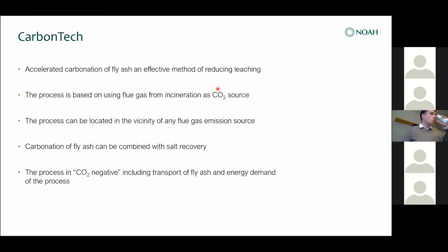And what is also important to us is that we can combine the carbonation of fly ash with salt recovery, because we can stabilize the fly ash first and then recover the salt later on. Always when we look at processes, we do life cycle analysis, and we also did that for the salt project, and it looks very good. This process is also overall CO2 negative. It means that we can capture more CO2 than we emit, including transport and the energy amount of the process. So it's a permanent capture of CO2.